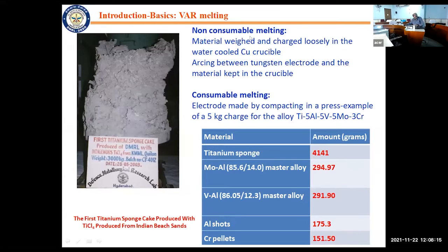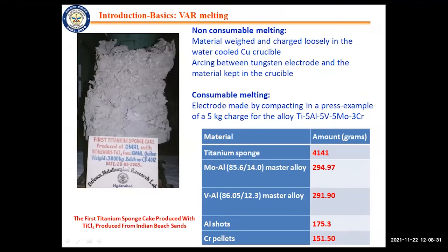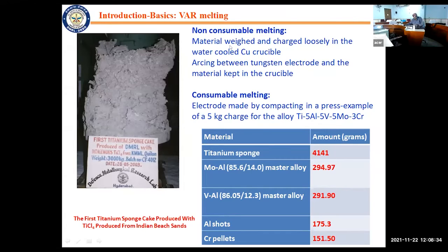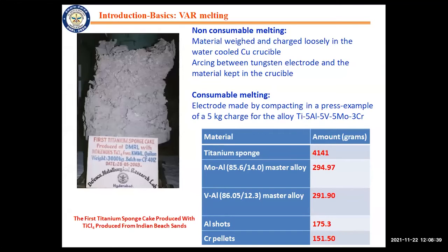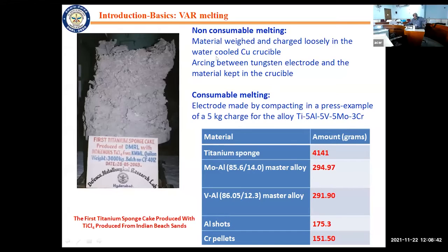Now, as far as titanium melting goes, it can be carried out in non-consumable mode or consumable mode. In the consumable mode, you melt the electrode itself, and you can melt larger quantity, right from 5 kg charge to any. Whereas non-consumable melting, you can melt smaller quantities, and there is a thoriated tungsten electrode, and arcing is between the material and the thoriated tungsten electrode, because the electrode is not melting. So that is why it is called a non-consumable melting.